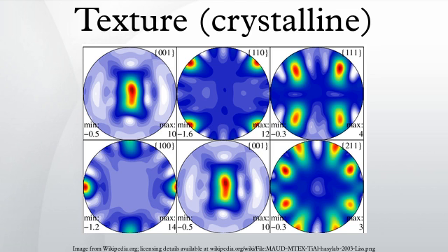The determination of texture gradients by X-ray scattering, however, is not straightforward, because different depths of a specimen contribute to the signal. Techniques that allow for the adequate deconvolution of diffraction intensity were developed only recently.